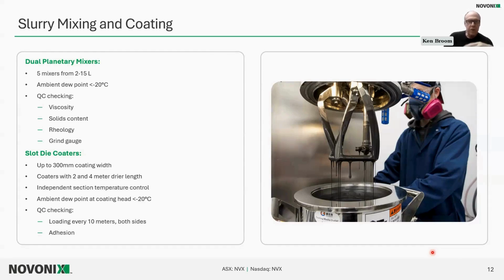And we do the usual type of QC checks that you would expect in this type of process. So viscosity checking, solids content, rheology, and grind gauge to make sure that the slurry quality is good. And sometimes at earlier stages, depending on the materials that we're working with the customer, we may even do smaller slurry mixes than this and just do hand coatings, grind gauge, and rheology measurements just to confirm that the material coats nicely before we go to full-scale coating.